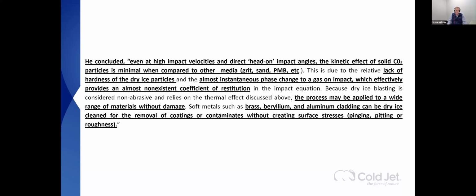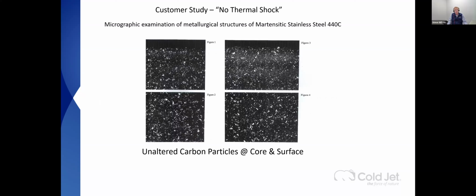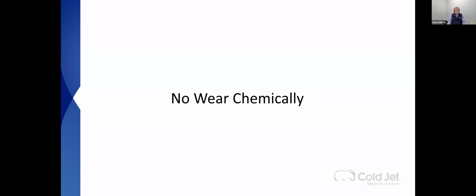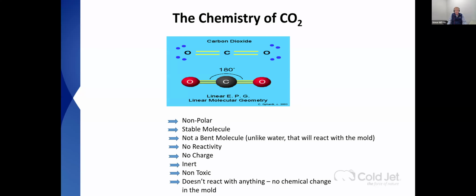It comes from independent studies that have been done. A customer did their own on thermal shock. They did their own studies on stainless steel 440C. After blasting on them, they found unaltered carbon particles, both at the core and the surface. After they did those tests, this customer put dry ice blasting to clean injection molds in 17 facilities around the world. Chemically, dry ice is a CO2 molecule. It's a linear molecule.